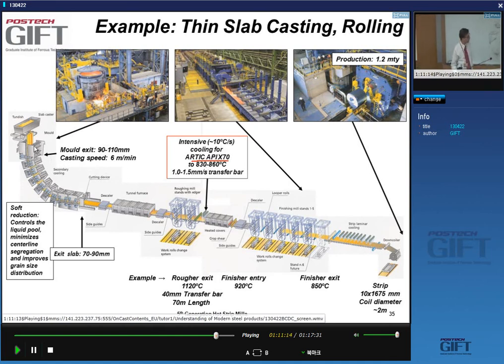Okay, so this, in contrast to the POSTECH line we just saw, this line is actually making relatively thick, 10 millimeter strip. But the technology is the same. You have a continuous caster, casting speed, again, maximum 6 meters per minute. You go through a tunnel furnace in this case. You have a descaler and then roughing stands.